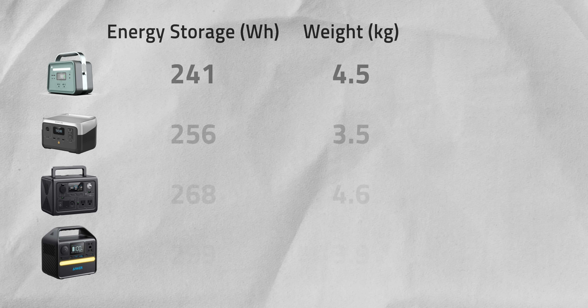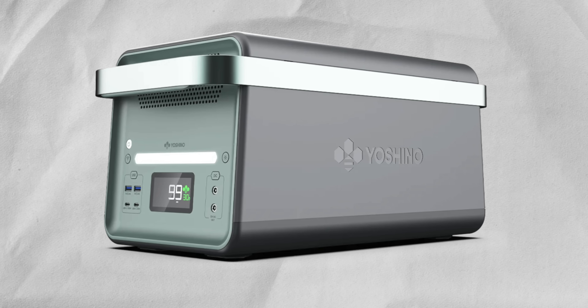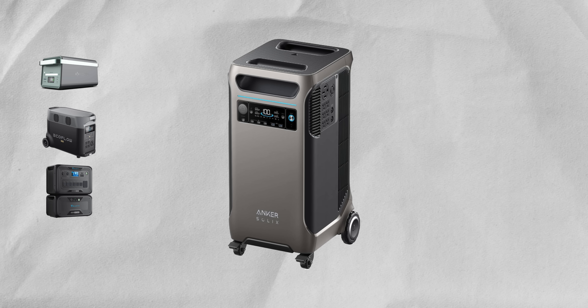The key benefits of solid-state are safety, longevity, and energy density. So how does it compare on that last one? Not so great for the model I've got. Yoshino is at 53.56 watt-hours per kilogram, which is just slightly lower than the Bluetti. But both EcoFlow and Anker have 73 and 76 watt-hours per kilogram. This made no sense to me, so I decided to expand my comparison to Yoshino's largest battery, the B4000, compared to the EcoFlow Delta Pro, the Bluetti AC300-B300 combo, and the Anker Solix F3800.